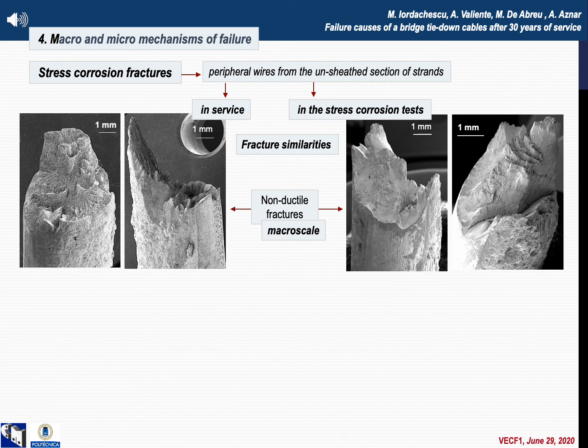The macroscopic images illustrate the fracture similarity of one of the peripheral strand wires broken in service with that of a stress corrosion under constant load tested wire previously damaged in service. Both are non-ductile ruptures. The only difference is given by the distinct oxidation of the fracture surfaces attributed to the exposure time of the first wire to the service environment after breaking.